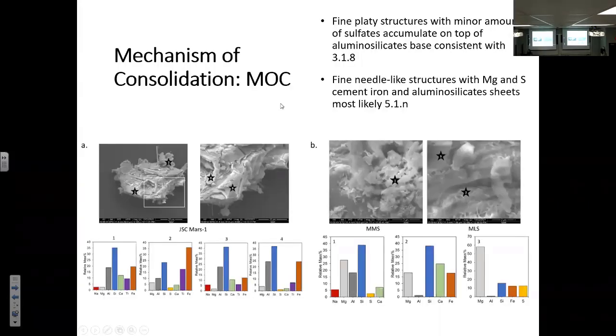When we looked at it closer, these are all zoomed in of the same images that we looked at earlier. The first one, A, is the JSC Mars 1 sample. These show you sheets of the JSC Mars, which was before this porous, fluffy looking structure. And now you can see that the main structure is mostly composed of the basic elements for the simulant, which is aluminum, silica, calcium, titanium, and iron. And between them, when we looked at these odd looking sheet-like structures, we see more of the magnesium sulfate coming in. So we suspect that this is how the physical entrapment mechanism works of MOC.